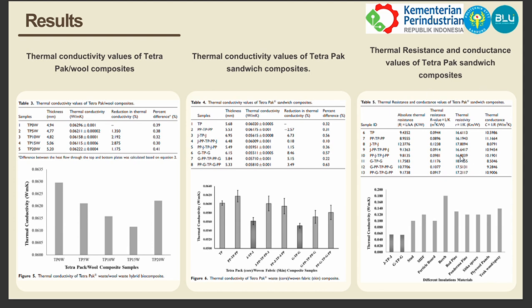And in the last figure, it is thermal resistance and conductance. Higher resistance, or we can say R, corresponds to lower conductivity, or we can say K. The glass skin plus 15% of wool composite shows the highest resistance and lowest conductance, proving it is the best insulator. Overall, increasing natural fiber ratio and adding proper reinforcement layers clearly enhance insulation efficiency.